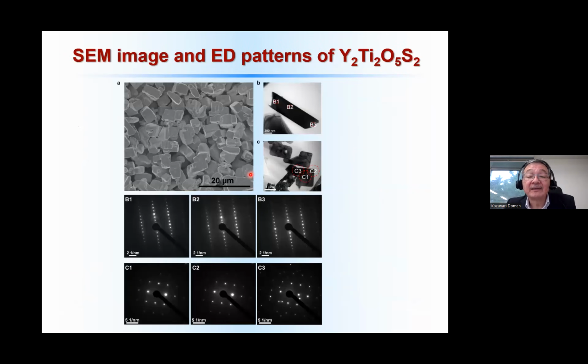And we prepared these materials at 800 degrees C in a vacuum sealed quartz tube for almost one week, so that the particle size becomes considerably large. This is a 20 micrometer scale bar. So the particle size is about 5 to 10 micrometers. This is not really suitable to use as a photocatalyst.